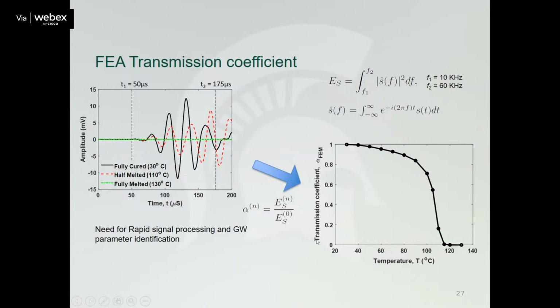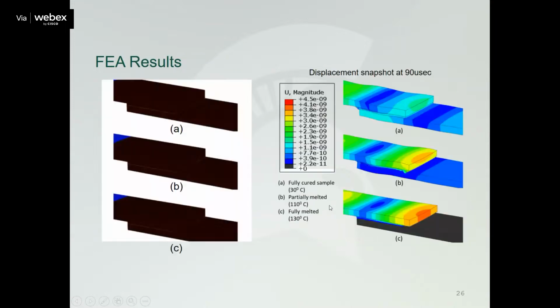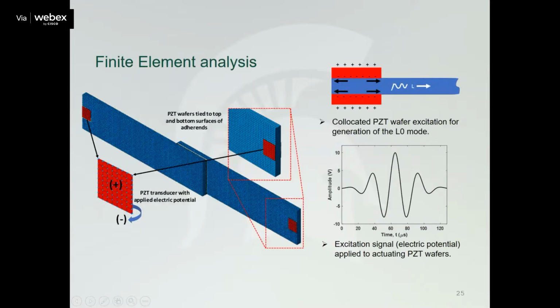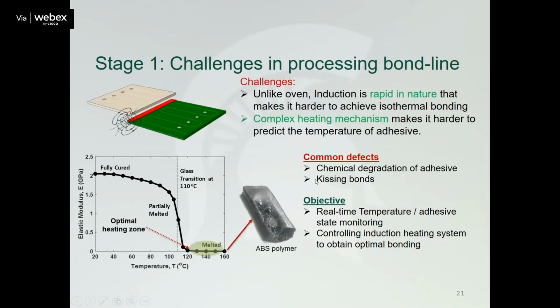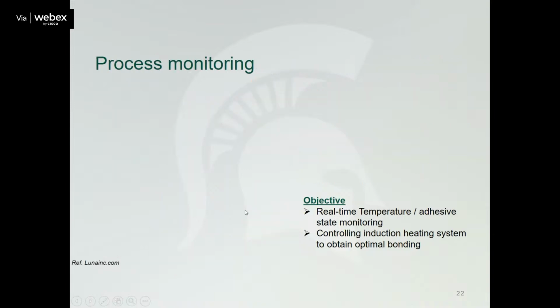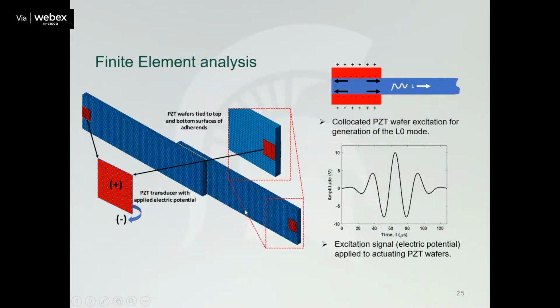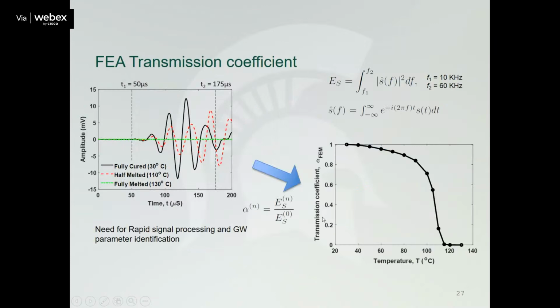And you can see the transmission coefficient versus temperature: you have a good transmission of energy for low temperature. When it goes to high temperature, it's melting, so you have less and less transmission from one to the other. Recall what we actually saw before. Let me show you. This is what we measured, the elastic modulus, and it's very similar to what we're getting here from the guided wave measurement, right? So this demonstrates that we can use this transmission coefficient to understand what's going on in the heat-sensitive adhesive layer at different temperatures.